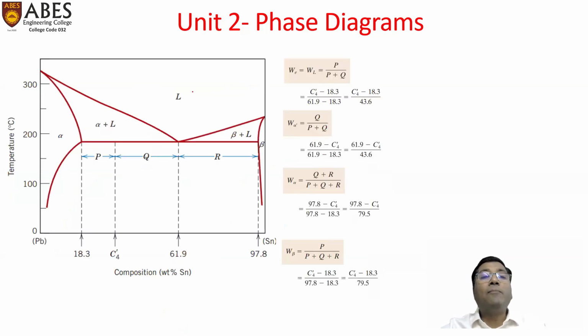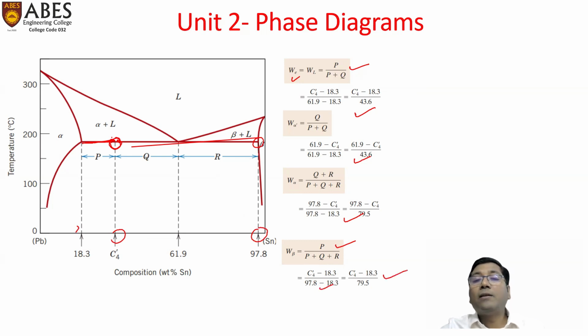And how can we calculate the mass fractions of those? Here it is written: W eutectic equals WL, which is equal to P upon P plus Q as per the lever rule. We can find out all these equations. And the mass fraction of beta at this point C4 dash would be the opposite arm, P divided by P plus Q plus R. Similarly, it is written here: P upon P plus Q plus R equals C4 dash minus 18.3 divided by 97.8 minus 18.3. So it will be this figure.